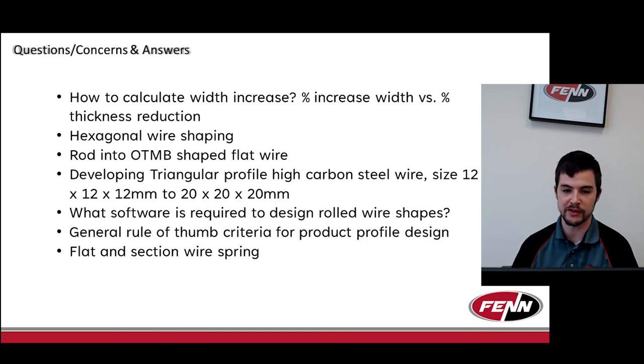So on wire mills in general, especially, that first hit is where you're taking the heaviest hit you can physically take in terms of reduction, with the biggest roll that allows you to take that hit, as well as working a little bit on the geometry roll to allow you to get that spread. And frequently what we end up doing is we try to overfill it, not dramatically over, but maybe slightly over the width you need. Then use a Turk's head to adjust and control the width, or an edger for higher accuracy at that point.